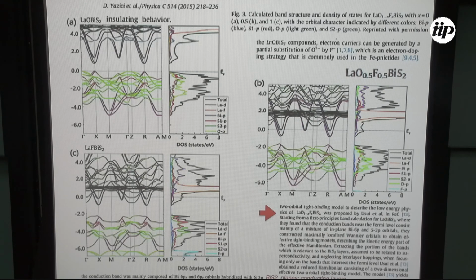So here, let me show you just a bit the kind of band structures obtained from DFT for these compounds. These, for example, appear in a review by Yazici and other people in 2015. For example, the parent compound for this one, which I was telling you, good single crystals are obtained. The parent compound is a band insulator. Some people say it's a semiconductor, but in principle, according to the results and most evidence, it's a band insulator.